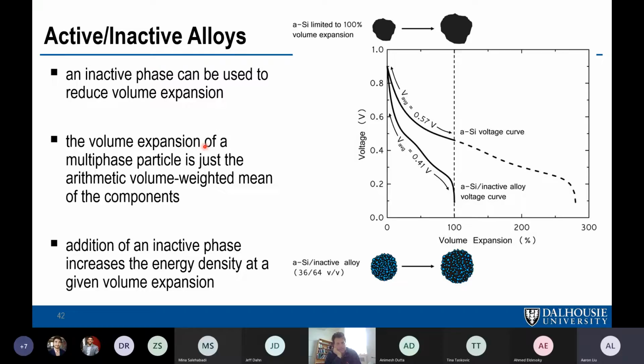If you have, say, graphite instead of the inactive alloy, you could go low enough to access the graphite capacity. Sure. I mean, this is going down to 0 volts here. If you have an inactive phase, you can go all the way to 0 volts and have 100% volume expansion. And if this phase happens to be graphite, then sure.